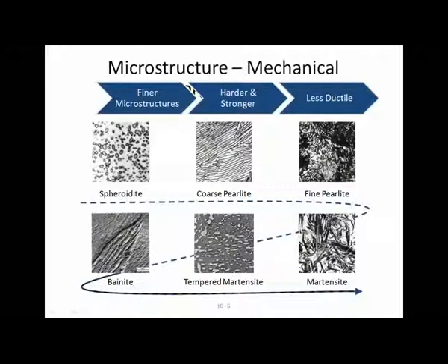Tempered martensite, the size scale looks very similar to spheroidite. So I said this was an SEM image, and this is an optical image. That's why the color of the particle separates out. With an optical image, we have to etch it to get the different phases to show up differently, which we'll talk about in corrosion. It's very cool. Corrosion for good, used for good purposes instead of evil. And then in an SEM image, the contrast of the phases, light versus dark, and what's what, is going to be very different because you're using electrons to image with instead of light. Any questions